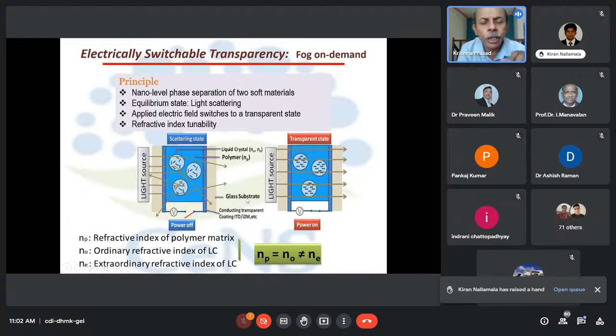Now I apply an electric field to the system, and I've already talked about dielectric anisotropy. Because of the dielectric anisotropy, it couples to the electric field, a torque gets applied on the system, and the liquid crystal molecules want to reduce this torque. They do so by turning themselves towards the electric field. That's why all the rods inside the droplets are now pointing along the electric field direction, which is applied across this panel. Since they're oriented along the electric field direction, the light beam sees the ordinary refractive index of these materials. The ordinary refractive index is equal to the polymer refractive index, so N naught is equal to Np, and you end up with a transparent state.